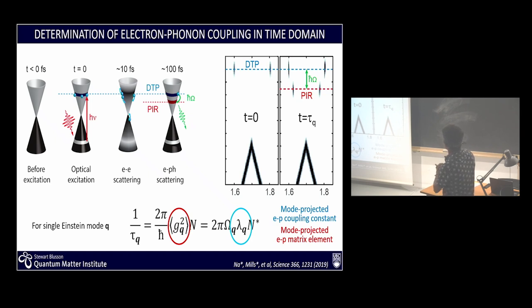And what happens? Well, here is a simulation done by Tom Devereaux's group at Stanford. Basically, you start off with an occupied state. You pump up into the unoccupied part of a Dirac cone. You now have two states you can see. But after a characteristic time, tau q, the electron-phonon scattering time, you start seeing intensity trickling down along the cone in discrete steps defined by the energy of the phonon itself.